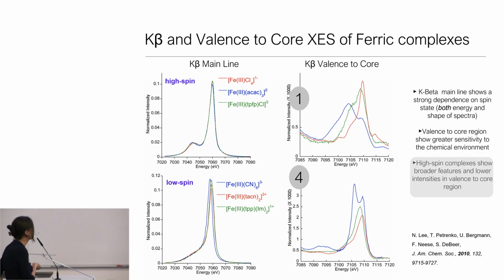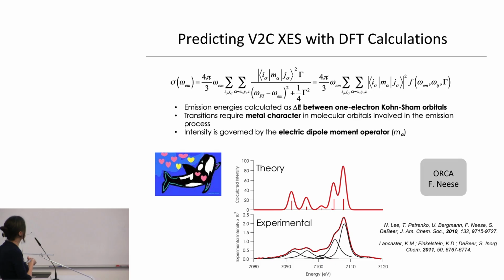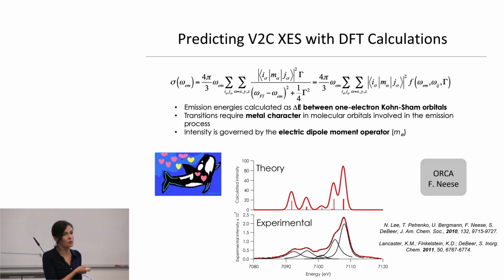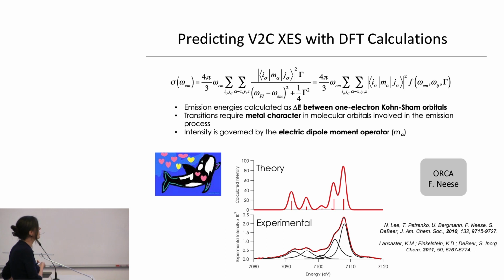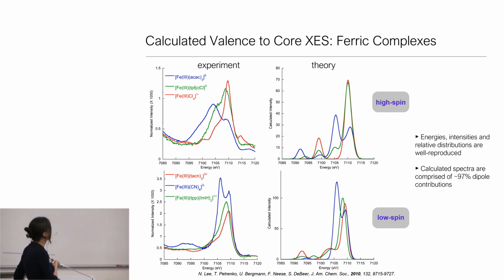And this is something that we've been interested in understanding through the years. This is something that you will also calculate in ORCA. And this is even more criminally simple than TD-DFT because this is really 1 electron DFT, just looking at the energy difference between the 1 electron Kohn-Sham orbitals and taking the dipole allowed intensities. But what we found very early on is that it actually did a really good job of getting correlations between experiment and theory. This happens to be the experimental and theoretical spectra for the ferric complexes, but it also worked well for the complexes in this study in terms of getting general trends.